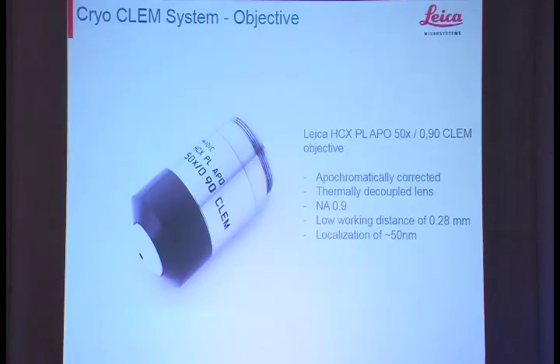One of the main features of this is the objective. This was developed by Leica, and it's got a ceramic nose so that it can withstand the around 200 degrees centigrade change in temperature from the cryo chamber through to the room temperature. And further up, there is also an insulating layer to stop this cold spreading through the rest of the microscope to give us some stability.